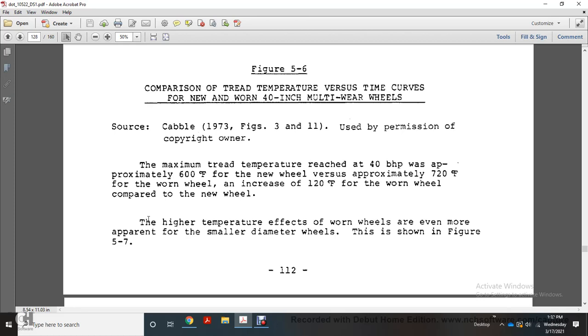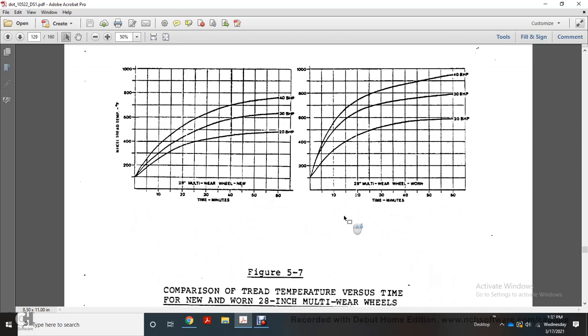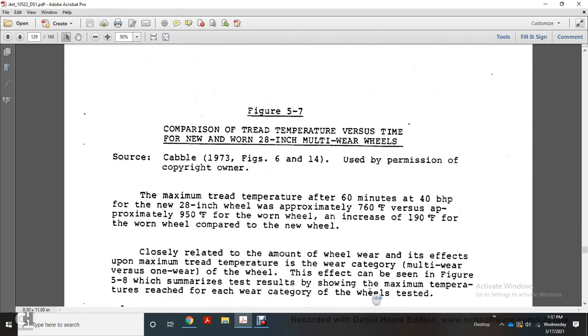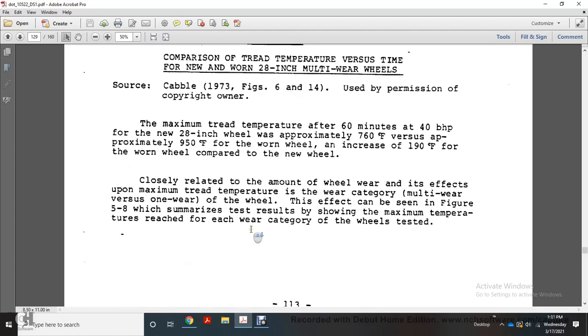The high temperature effect of the worn wheel compared to the new wheel is even more apparent with small diameter wheels. This is shown in figure 5.7. Figure 5.7 shows the comparison of tread temperature versus time for the new and worn 28-inch multi-wear wheels. Maximum tread temperature at 60 minutes with the 28-inch wheel at approximately 40 bhp is approximately 760 degrees Fahrenheit versus approximately 950 degrees Fahrenheit for the worn wheel, an increase of 190 degrees Fahrenheit for the worn wheel compared to the new wheel.